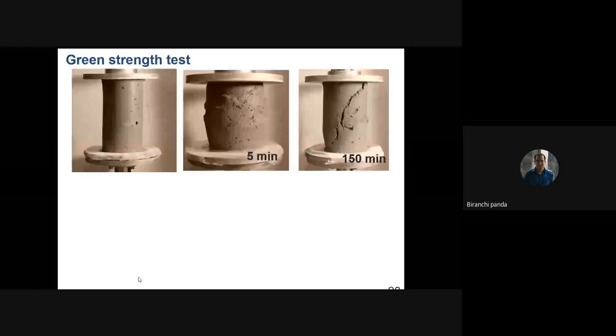So we initially took the fresh mix and compressed it at 5 minutes. Then the same test was repeated after 150 minutes. Because we know that if we are planning to print a tall structure, we'll still be printing the material after 150 minutes. So we wanted to see what changes are happening to our material once it crossed 150 minutes. For that reason, we conducted this green strength test. It's called green because the material is very fresh. You can see at exactly 5 minutes, if you compress, it is going to deform very easily. But if you wait for 150 minutes, the material slightly hardens and you'll get a shear crack if you test under compression. So we captured this material behavior with respect to different time intervals.